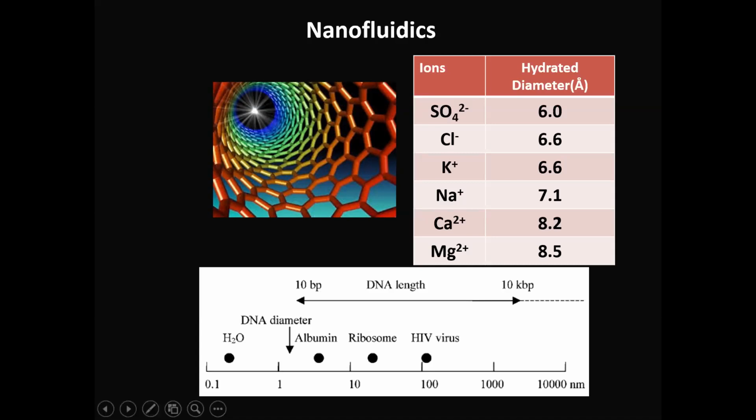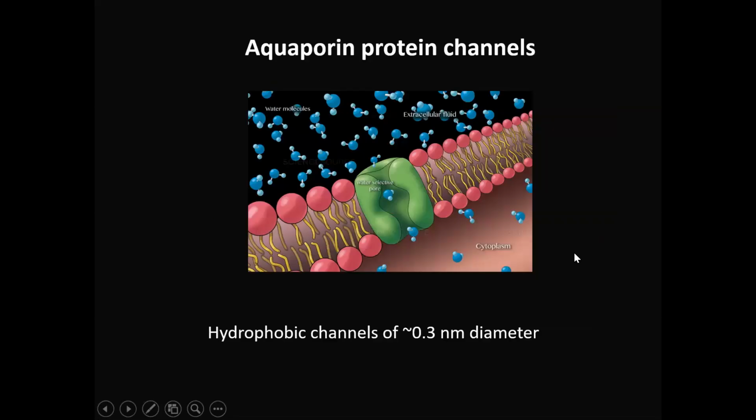But then, how can you make it so small? For example, I want to make it 1 nanometer. Is it possible to make such a structure with lithography? It is almost impossible. So then we came up with this idea: why don't we use the thickness of the 2D materials? Because thickness is actually very small. You can go to 3.34 angstrom. So that is the idea, and we ended up making fluidic channels or membranes with lithography and 2D materials.